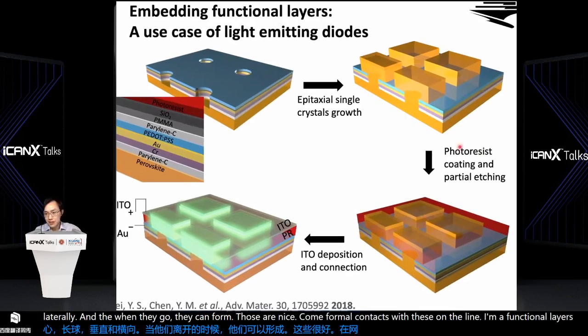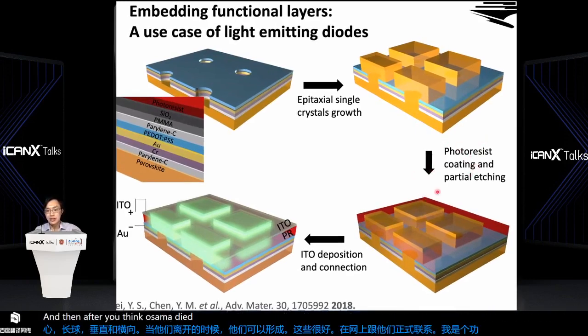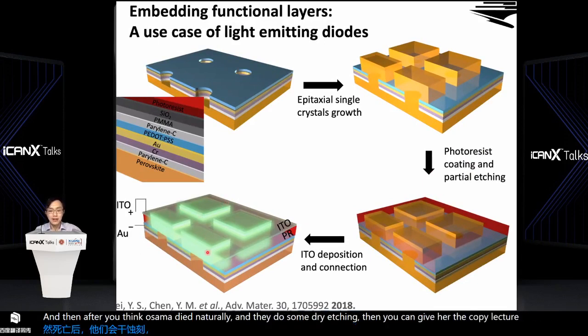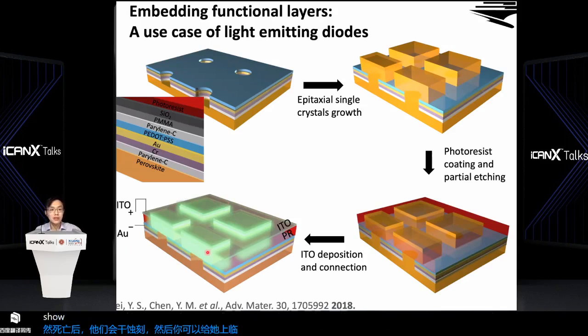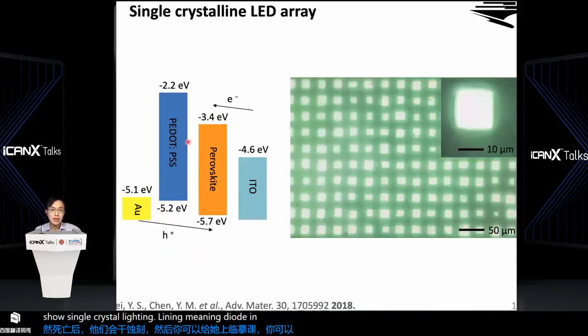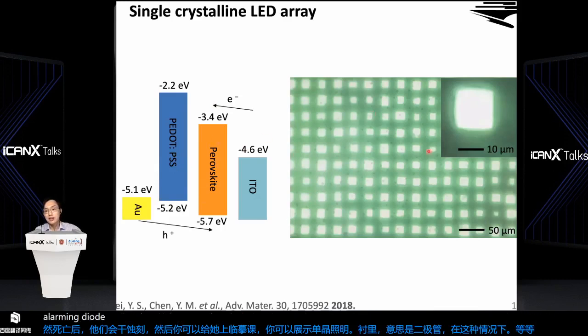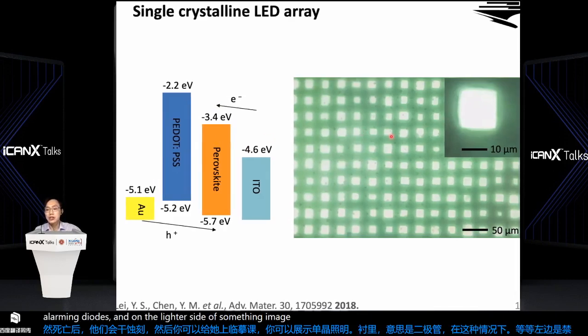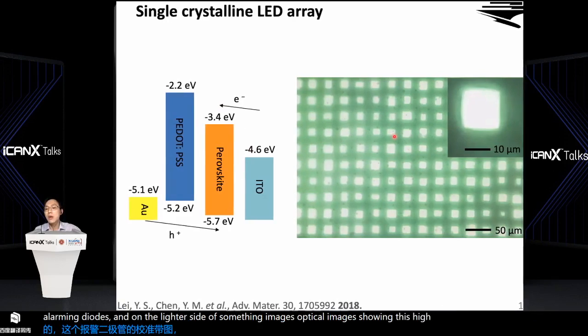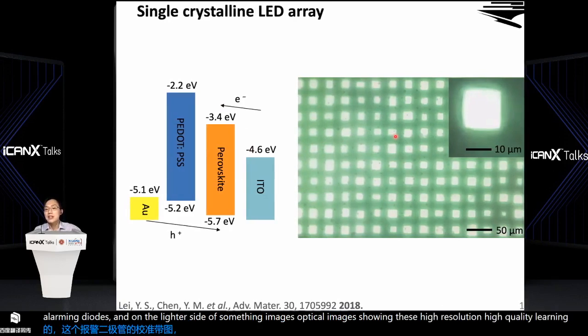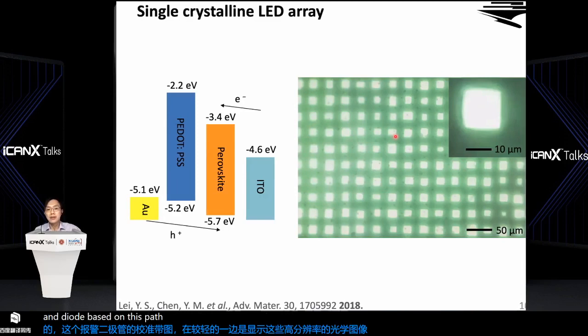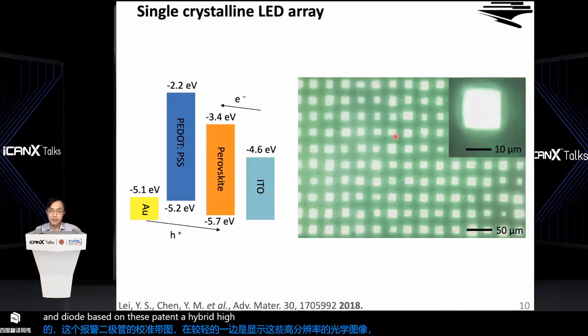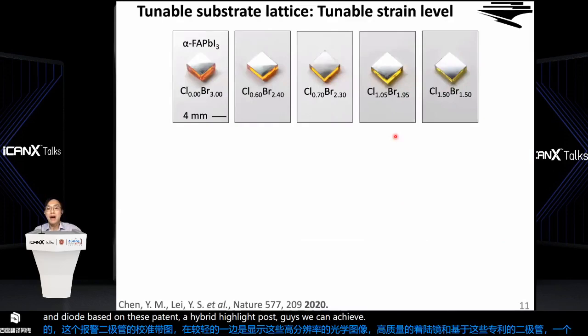And after you deposit some dielectric layer and do some dry etching, then you can deposit the top electrode, and you can show a single crystal light emitting diode in this case. On the left-hand side is the band diagram of these light emitting diodes. On the right-hand side are some optical images showing the high resolution, high quality light emitting diode based on these patterned hybrid halide perovskites we can achieve. So this is a very powerful platform.